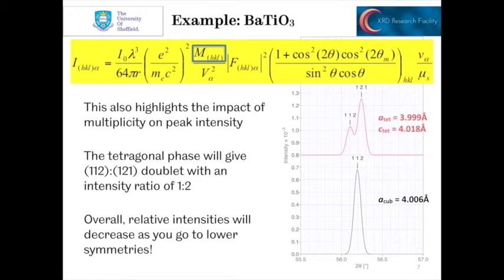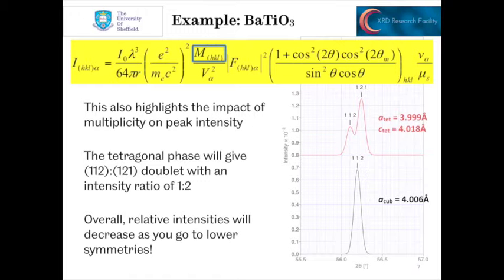You can imagine if we went to a monoclinic phase or a triclinic phase — something with a lot less symmetry — we would suddenly have a lot more peaks because the peak overlap would be much reduced in those systems. That also explains why, if you're looking at something that's monoclinic or triclinic, you're going to have to run for a lot longer to get similar intensities as you would for a cubic material.